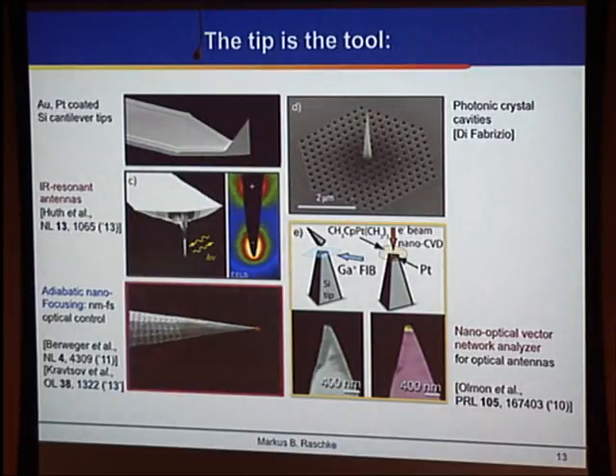The tip is, of course, the tool, and I mentioned already that the optical antenna properties matter. So we can engineer structures where we either have resonant interaction of the driving field with a finite length metal wire. We can transduce the excitation into this apex localized field through combination with photonic crystal structures. One primary tool I'll show you in the end, because this allowed us, in fact, to do very high contrast nonlinear ultrafast imaging, where we couple the light not by directly illuminating the apex, but by having a coupling structure distant from the apex, where we launch a propagating surface wave which adiabatically compresses into the apex, so we can really generate a few femtosecond pulse in a few nanometer volume.